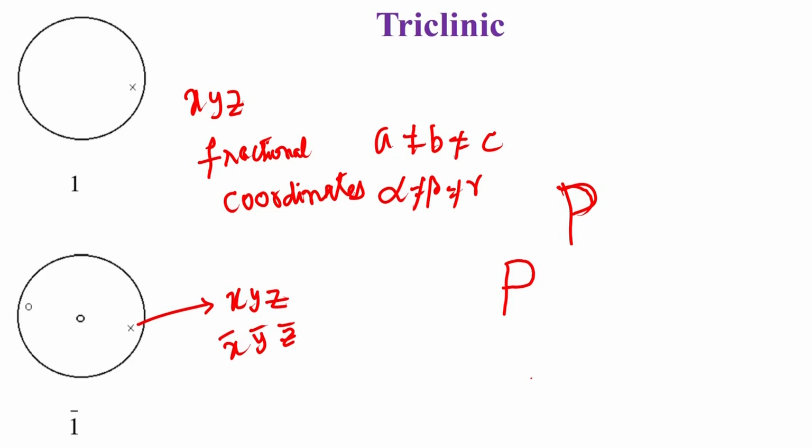So, when we write a capital P and say it is a triclinic system, it can have only 2 of the symmetry elements which can be associated with this lattice. So, the first one will be P 1, and the second one will be P 1 bar. So, there are 2 possibilities to combine the lattice symmetry with the symmetry that is associated with the crystal system.